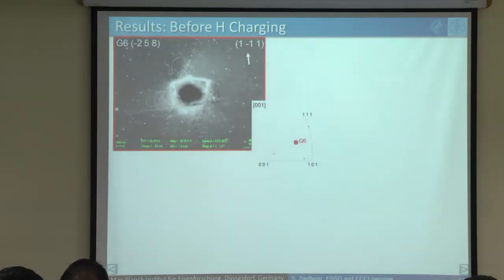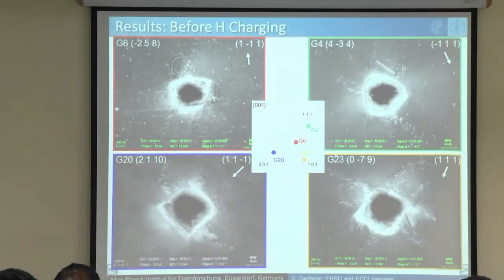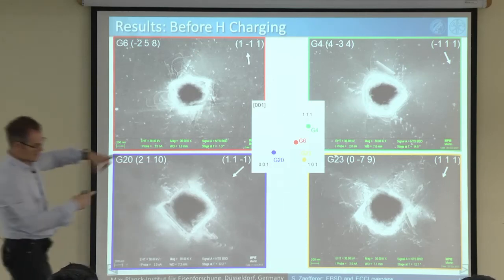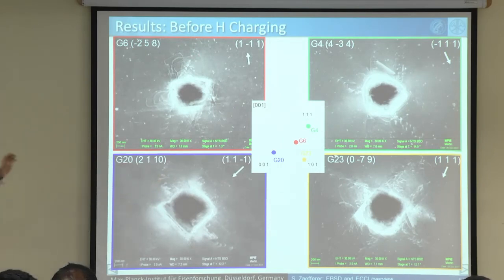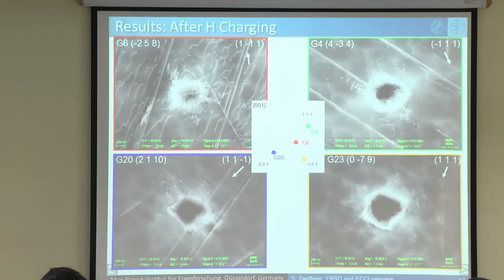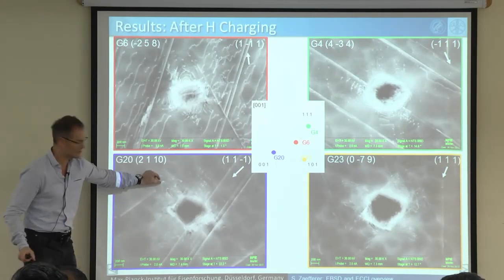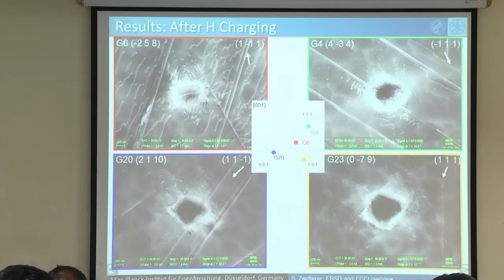For this presentation, I selected just 4 grains, each with a different indentation direction. And in each one, you see very characteristic dislocation systems being formed. Of course, you see the symmetry of indentation, but you also see how many dislocations are excited and how dense they are and so on. You see a lot of information. And then I polished and charged the same thing with hydrogen and looked into exactly the same crystals again. So this is before, without hydrogen, and this is after hydrogen charging. Now I compare the densities and the splitting of the dislocations, and I understand a lot of the effect of hydrogen on this material.